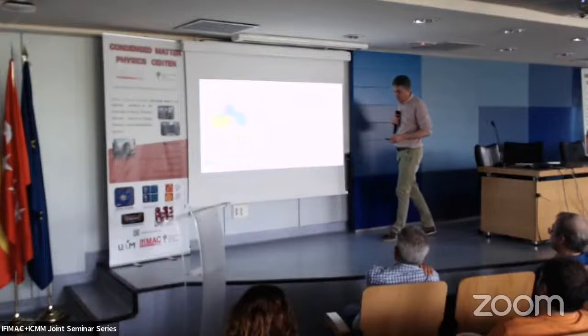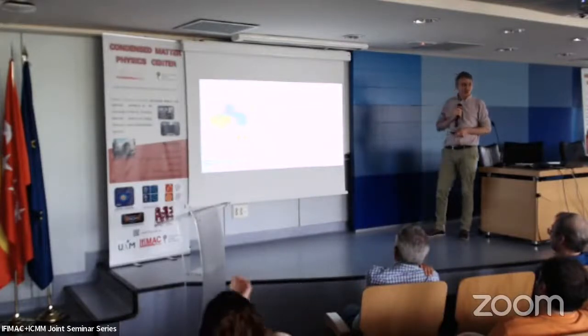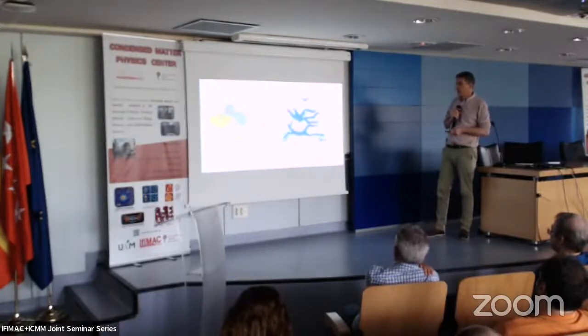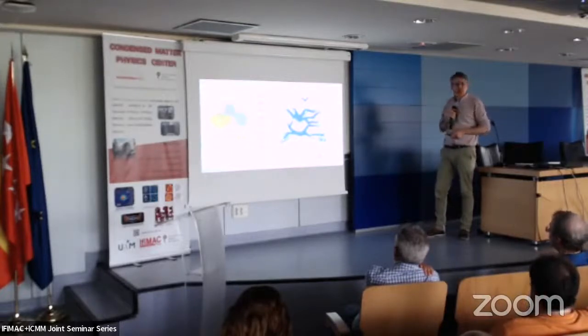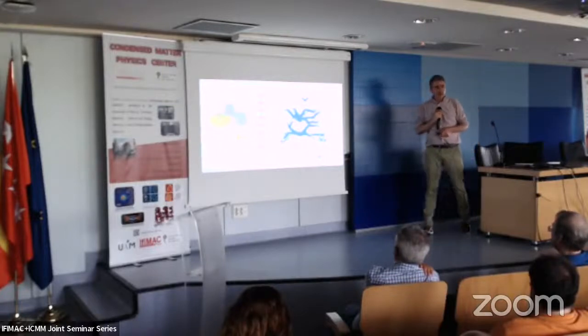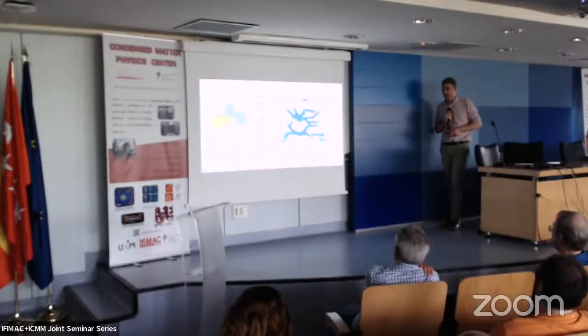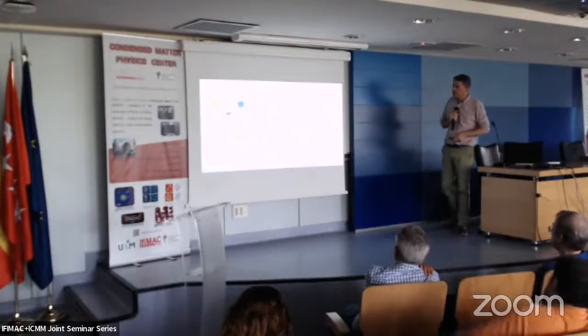We of course need some band structure calculations to see what happens here, and I would like to show you that this here is actually very well reproduced by the experiment. This is one of the few F electron systems where you can use DFT, and here there is a gap. We contacted the people who made this calculation, and they made a nice slab with the uranium atoms, and they found that exactly at this position here there is a very shallow band with a mass which coincides with the mass which we observe in our experiments.